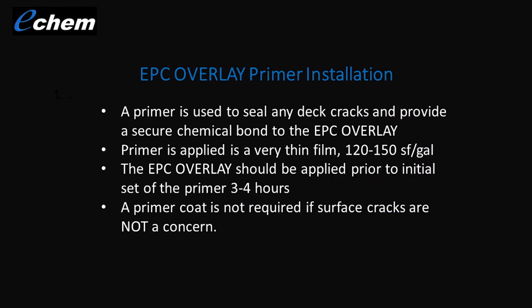Primer installation: the reason we use a primer or pre-treatment is to address any surface cracking. We want to make sure we address surface cracks, we fill them. That way, it's kind of a belt and suspenders application, so we can fill and seal off any subsurface cracks there.